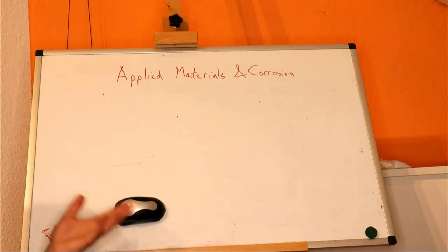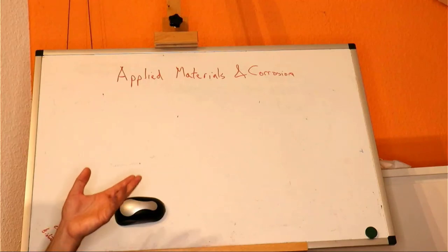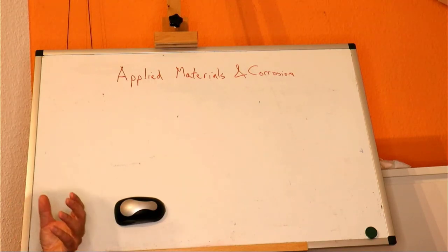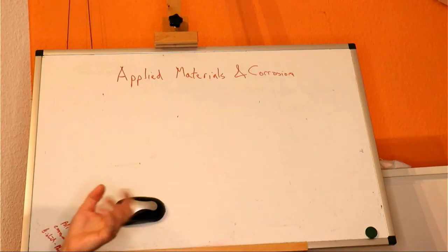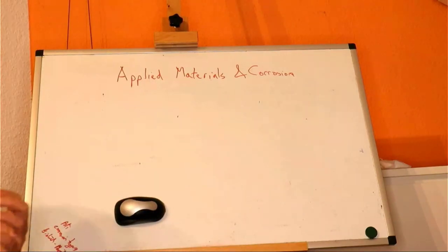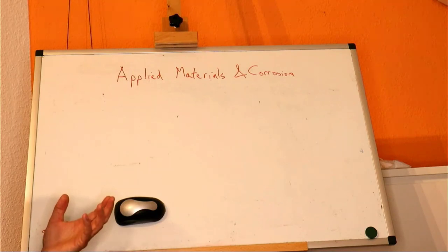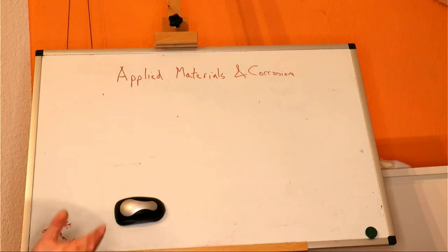So from the point of view of designing processes, it is better to block it in different ways. The traditional way to prevent cathodic delamination is to have a chromium salt, because the chromium salt became reduced in the region where the oxygen will be reduced and blocked it instead, and the other end became oxidized, and that was very handy. These days we can't do that, because of the toxicity of chrome 6, by the way, so we have to use other processes. We have other solutions, not as good, but they are not as toxic either, and vehicles tend to last long enough anyway, unless we happen to be close to the coast or they spray a lot of salt on the road, in which case we will be corroded pretty much whatever we do.